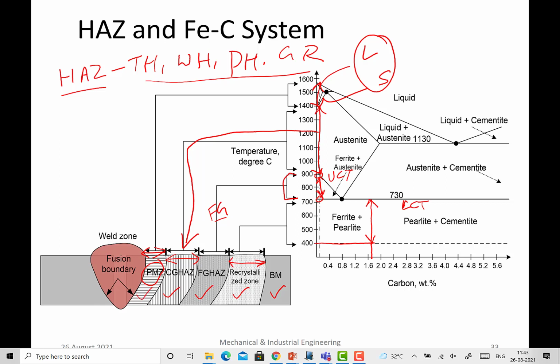Now depending upon the composition, if the carbon content is a little more, you may get martensite very easily, or it may be a mixture of martensite and pearlite. Here you may get fine pearlite, okay, or fine martensite as well. The recrystallization zone may have just newer grains of ferrite and pearlite, okay.